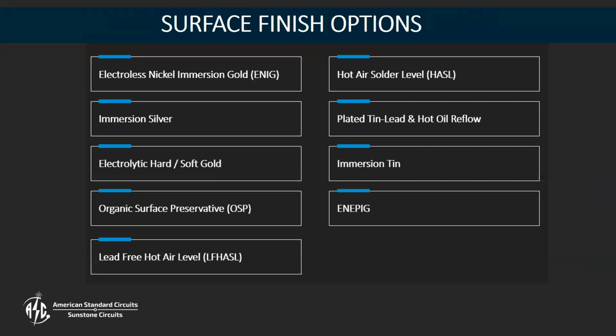After silkscreen, we apply our surface finish. For the most part, there's a couple, like electrolytic hard or soft gold actually gets done prior to solder mask addition, but the rest of these surface finishes are done after the solder mask and silkscreen are done. So you've got ENIG, you've got immersion silver, electrolytic hard or soft gold, OSP, solder, whether that be lead-free or leaded, hot oil reflow, which again is done before solder mask, immersion tin, and ENEPIG are some of the most popular surface finishes available.